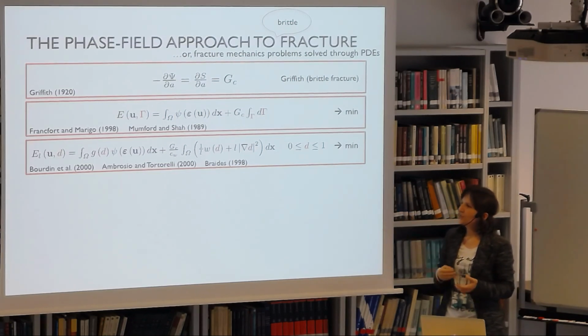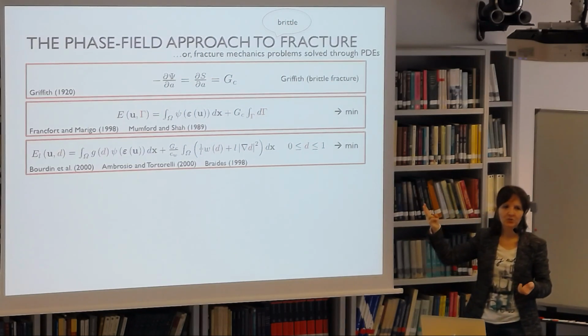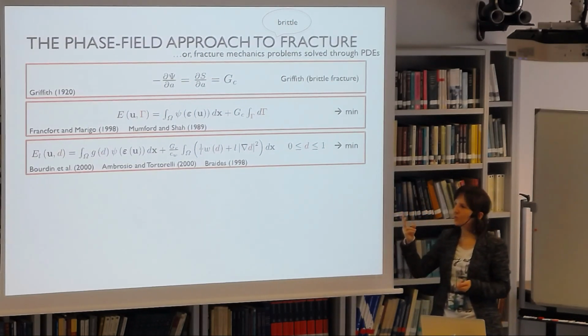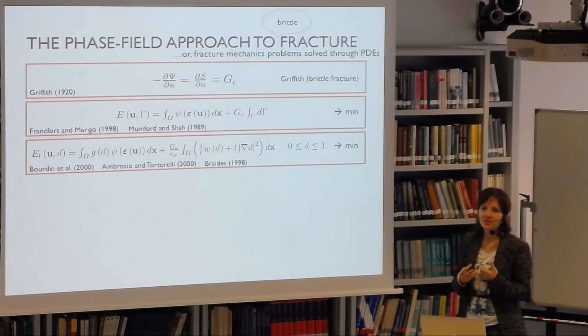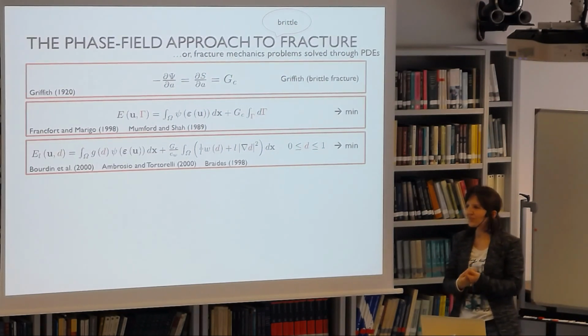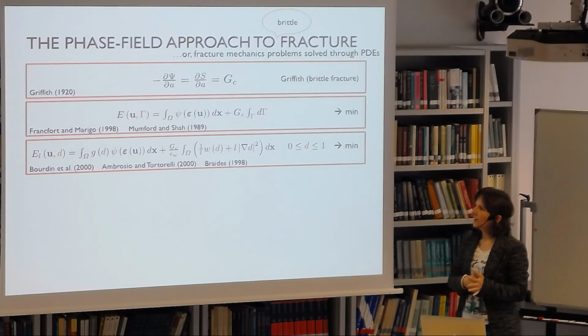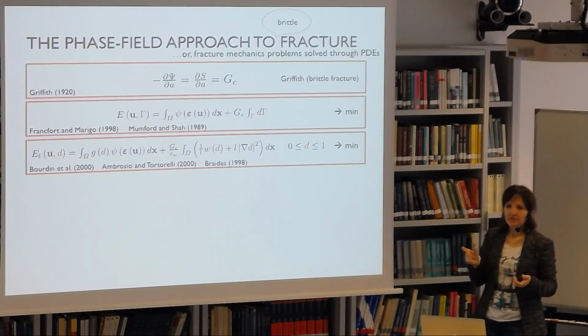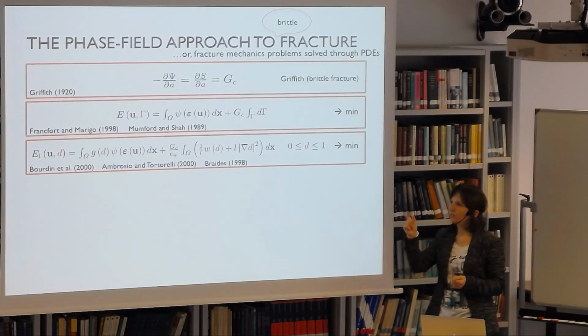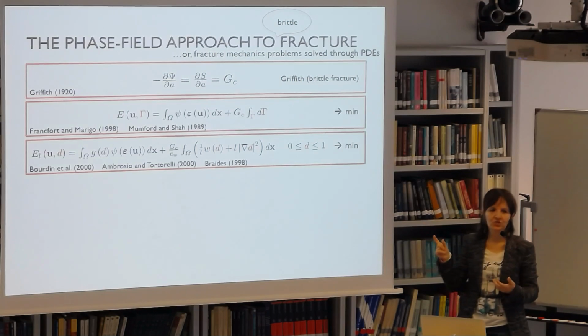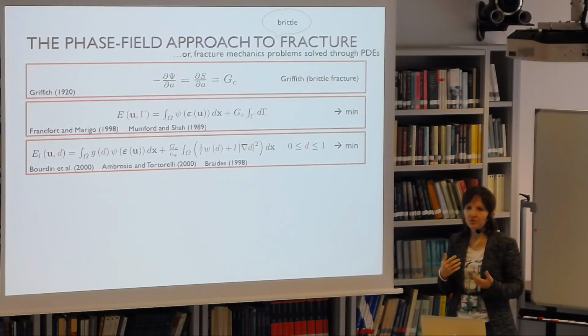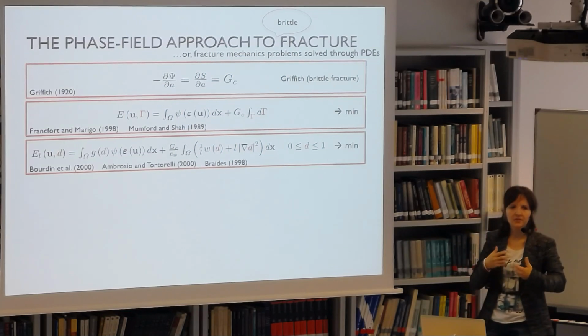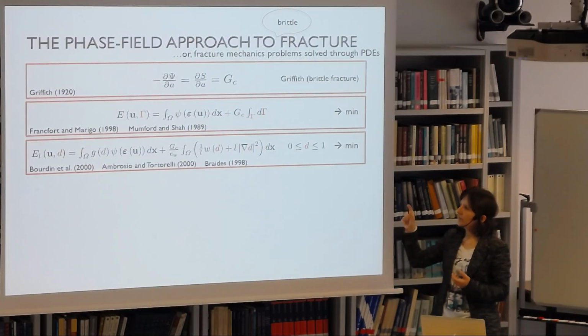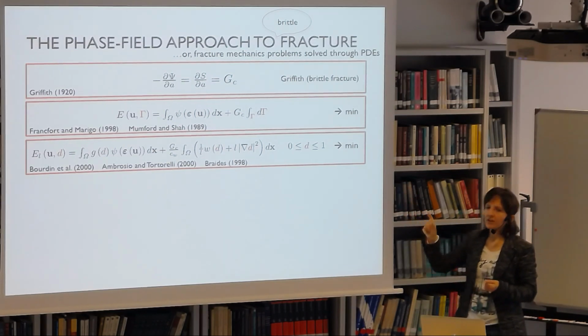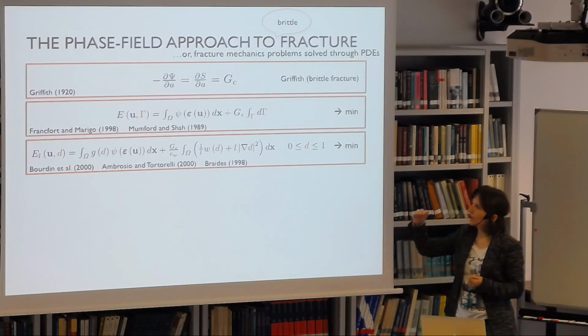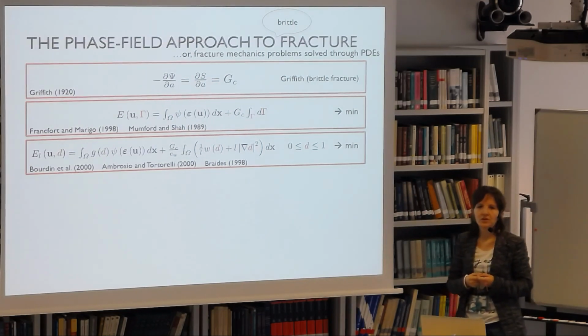So in this functional, you see that now we have again two arguments. One is the displacement field as before. The other one is what we call the phase field, but you can also think of it as a damage variable. I actually like to think of it as a damage variable. That's why I like to call it d. The first integral is again the elastic strain energy, but now you see that we have a function that we call the degradation function, g of d, which is basically degrading the elastic properties of the material as the damage is progressing. And the second integral is, as opposed to before, now again a volume integral, and it's a regularization of the previous integral over the crack set.